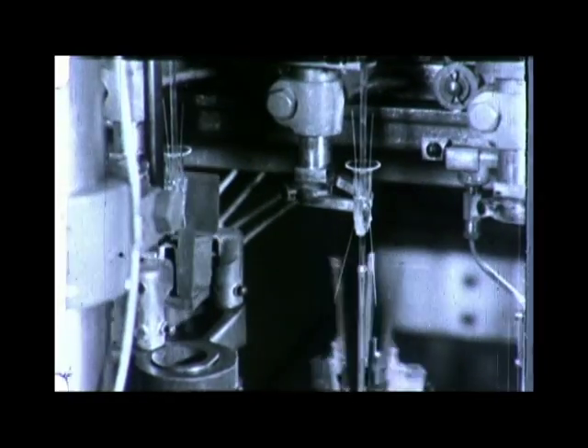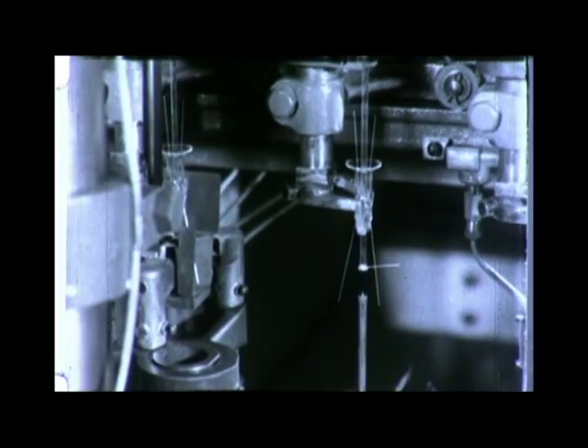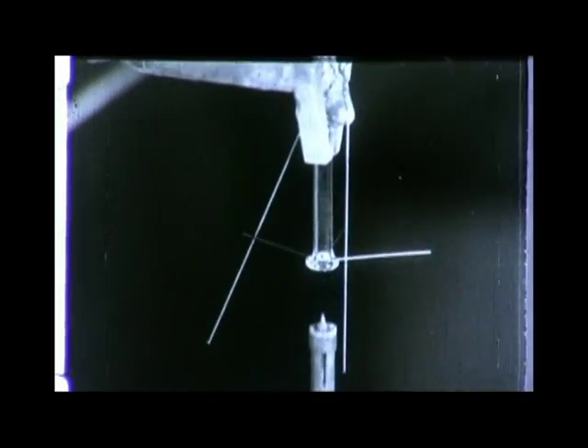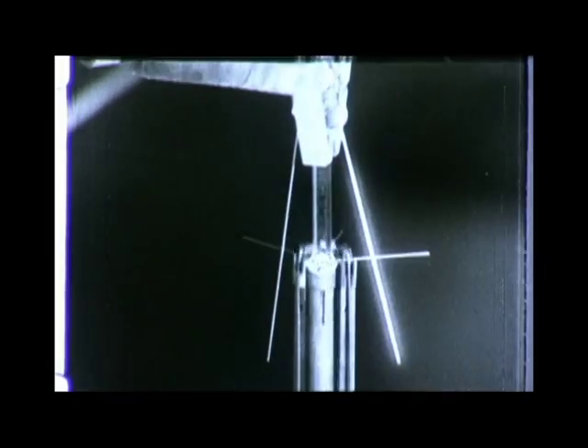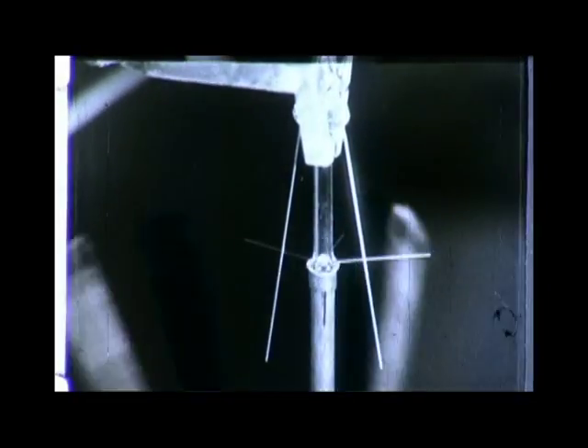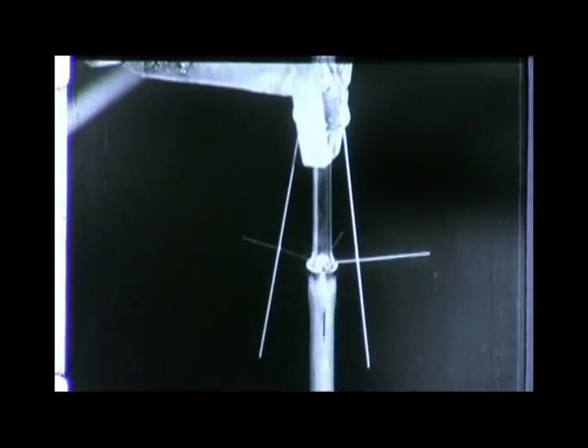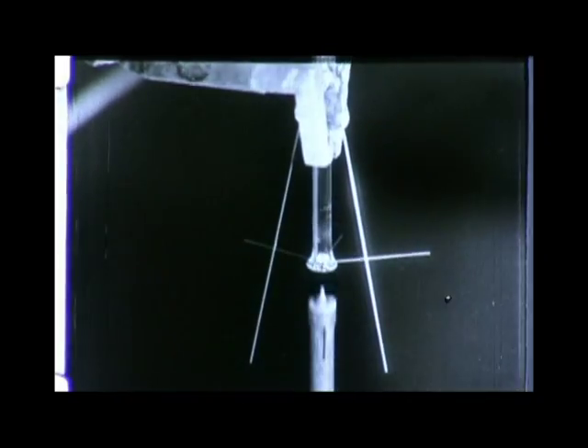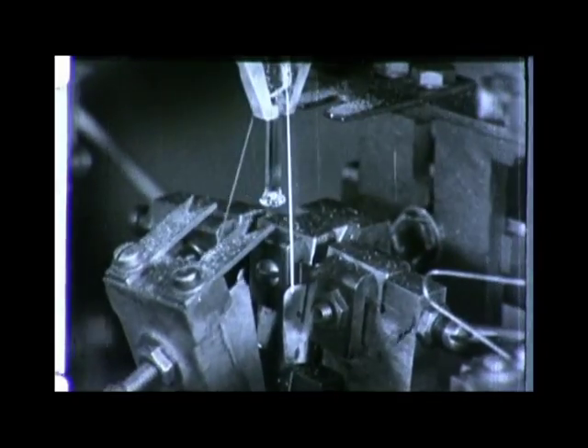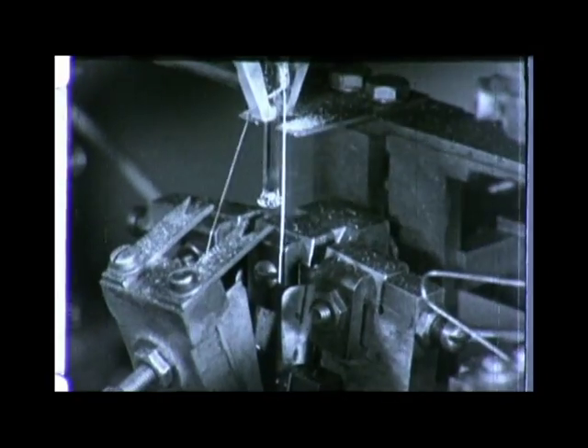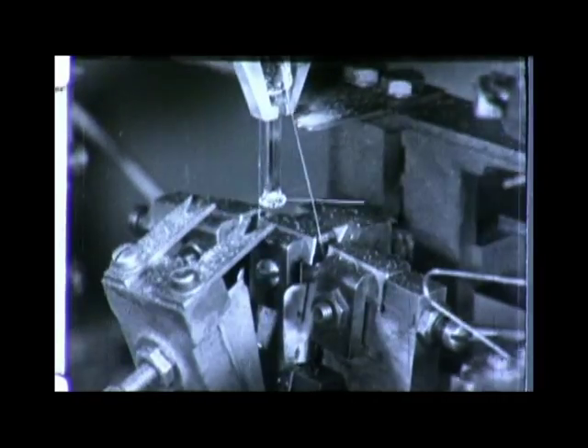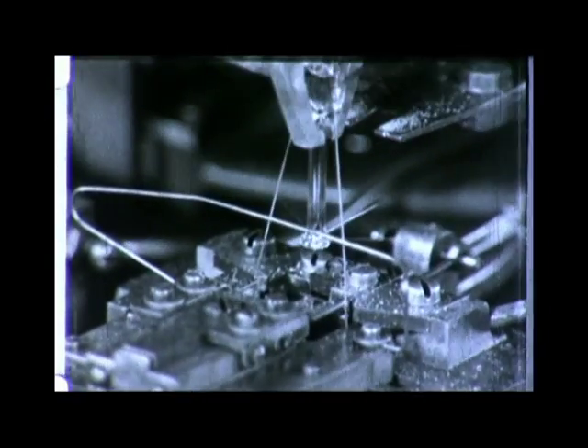Here the so-called buttons and supporting hooks are applied. You can see these two things happening simultaneously. At the end of the stem tubing, a small flat button is made, and at the very same instant, 3 short supporting hooks for the filament are embedded in the softened glass. To ensure a better clamp for the filament, the ends of the lead wires are flattened. Then a hook is made in each flattened part. Within this hook, the filament will finally but firmly be clamped.